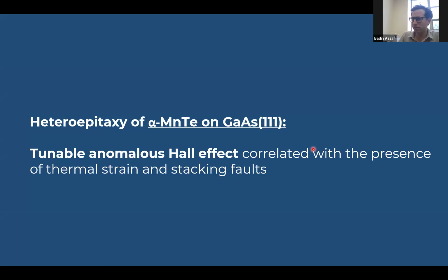That's what we've done beyond this study. We've studied heteroepitaxial manganese telluride grown on gallium arsenide. And there, we've seen a specific type of stacking fault and a specific type of strain whose appearance correlates with a surprising anomalous Hall effect.